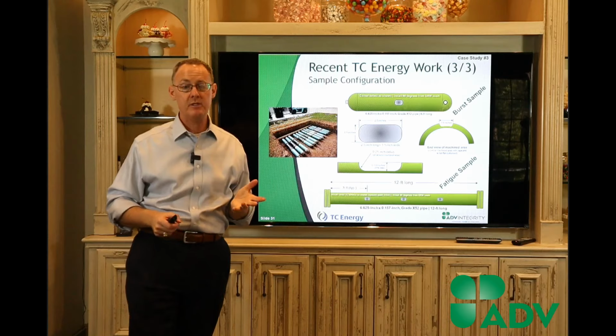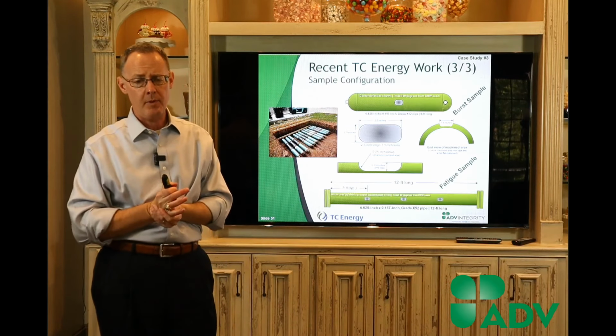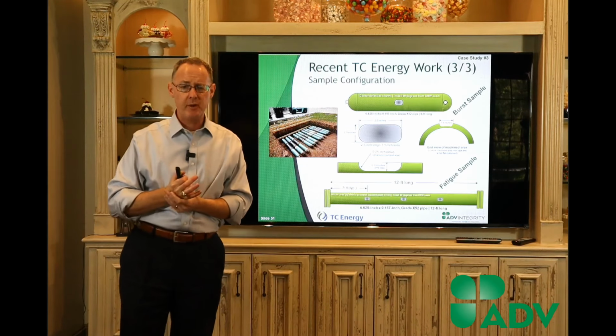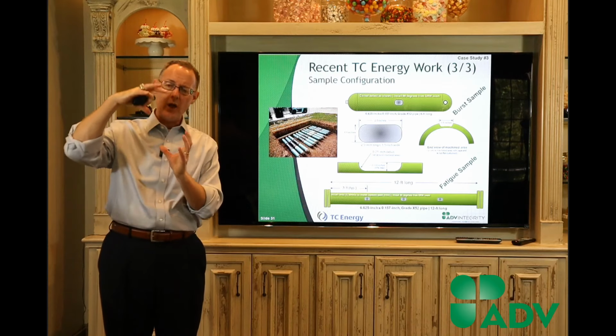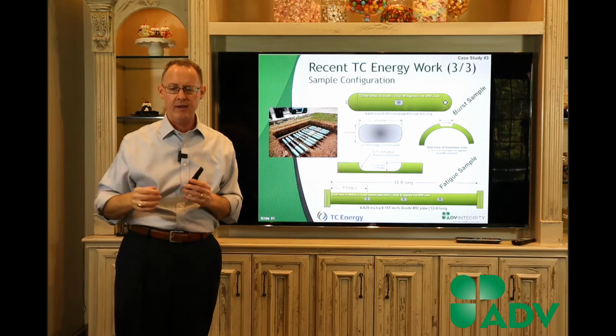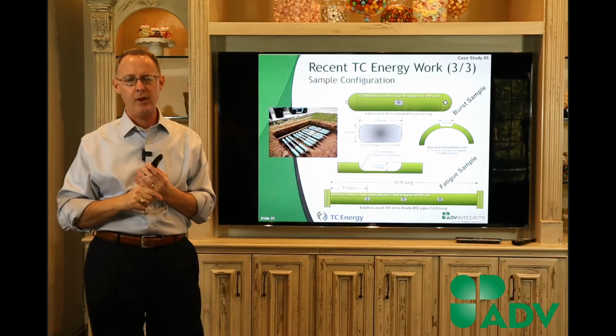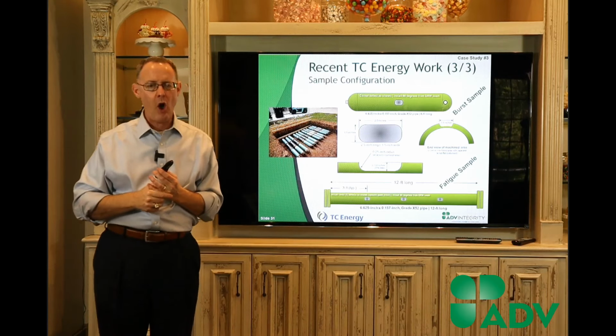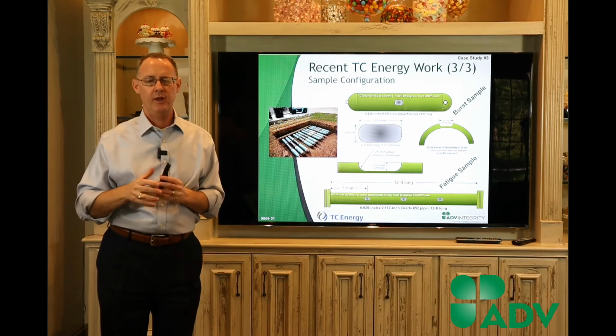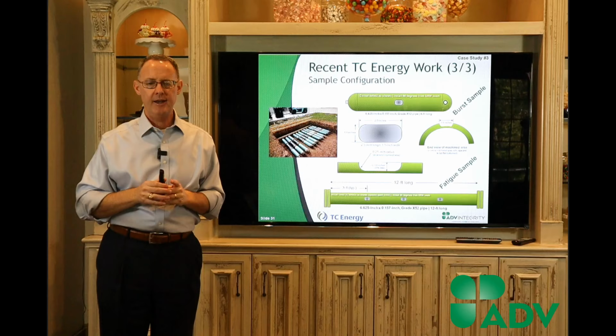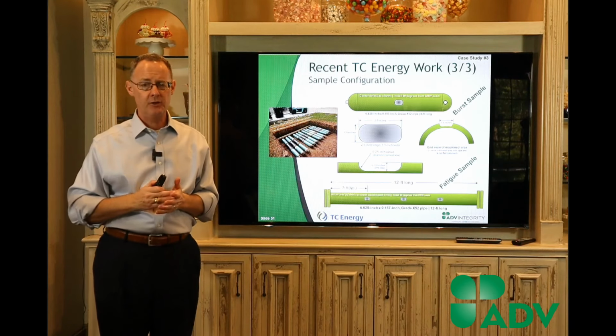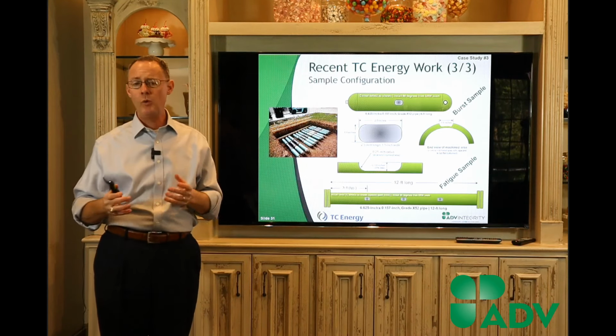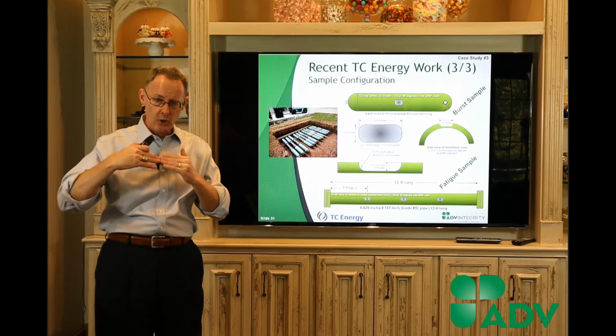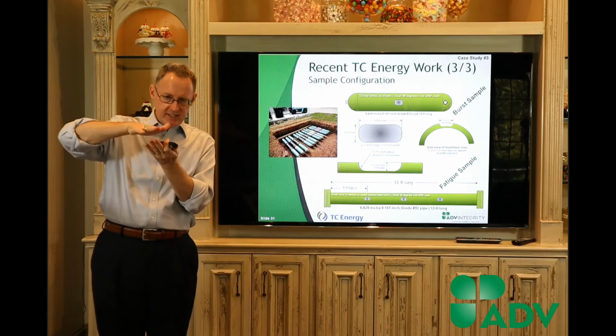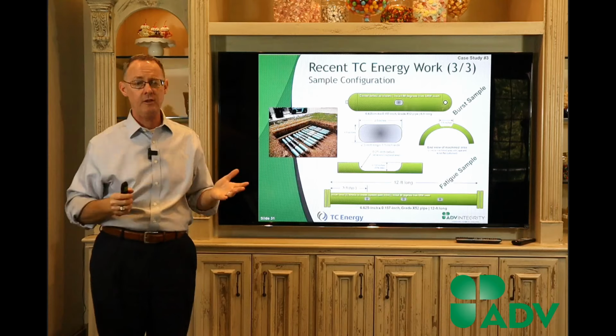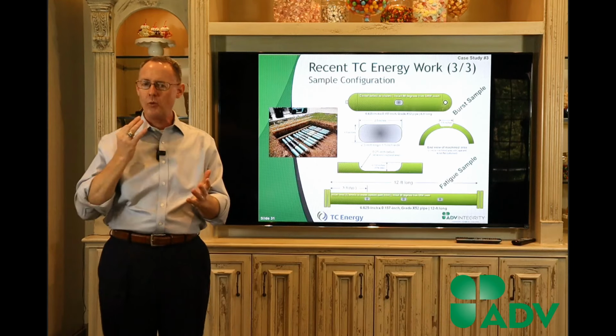And we had two companies that participated that we'll talk about in the paper. One was Western Specialties Composite Sleeve, which is a steel half shell that's glued on the pipe. I've tested that technology for probably over 10 years and have always gotten extremely good results. And it's an alternative to welding. You're adhesively bonding that steel sleeve. So it does real well in leak repair because as that corrosion wants to bulge out, you've got steel pushing it down.